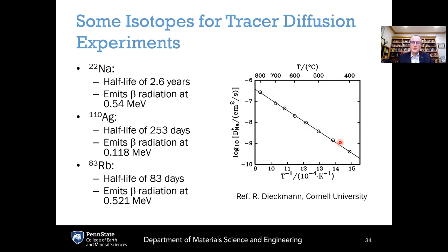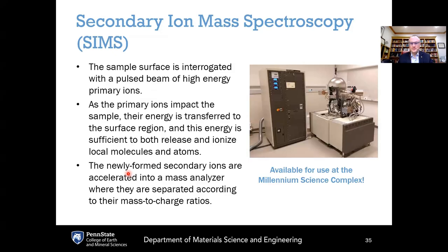So this shows Arrhenius behavior, and that Arrhenius behavior, then the slope can give you the activation barrier for the diffusion process. A couple of examples of other isotopes that can be used are silver-110, which has a half-life of 253 days, and rubidium-83, which has a half-life of 83 days.